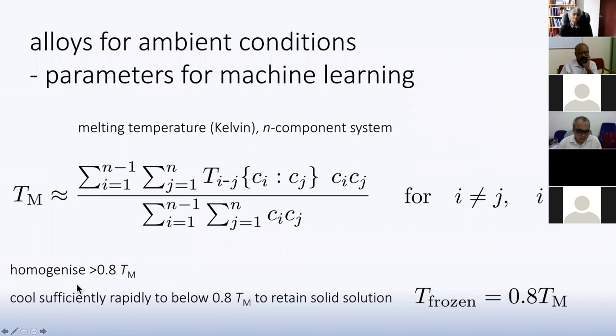And in general, if you want to homogenize a high entropy alloy, you should do it at a temperature which is 0.8 of the melting temperature. Okay, and then cool sufficiently rapidly, and that's not a very high cooling rate, but I mean, don't dwell at intermediate temperatures for a very long time, because the structure essentially then can be considered to be frozen below about 0.8 TM. Now, this equation looks very complicated, but actually it isn't.